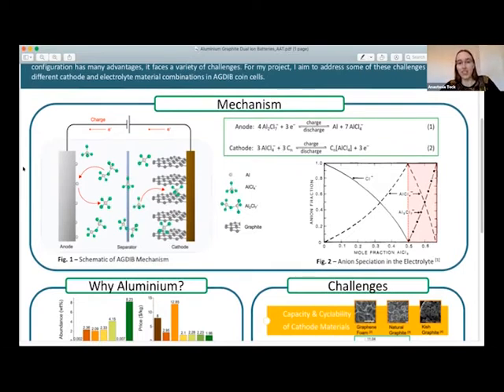This means that during charge, two different anions move from the electrolyte to the electrodes. At the anode, di-aluminium heptachloride (Al2Cl7-) causes electrodeposition of aluminium metal, while at the cathode, tetrachloroaluminate (AlCl4-) intercalates into the graphite interplanar space. And the reverse happens during discharge, of course. The ionic liquid electrolyte that is used is a chloroaluminate melt, which contains both the required anions at certain conditions, as shown in this anion speciation diagram in the region shaded in red.